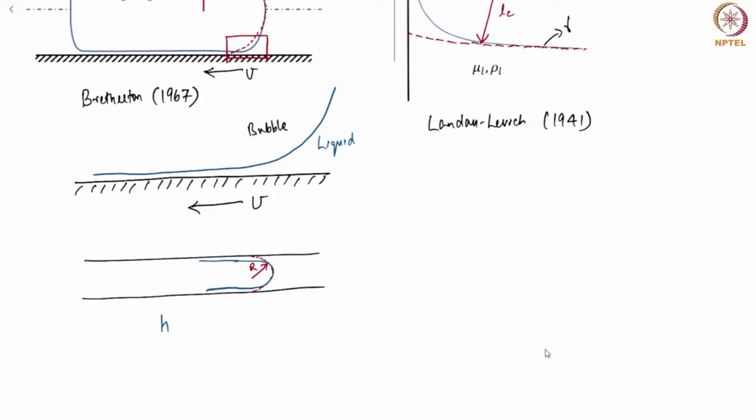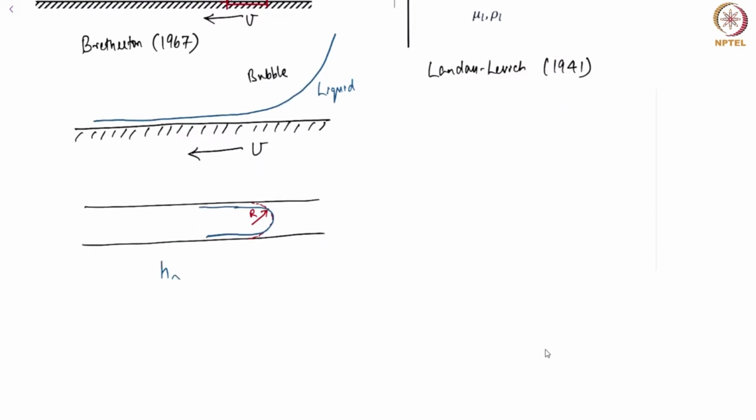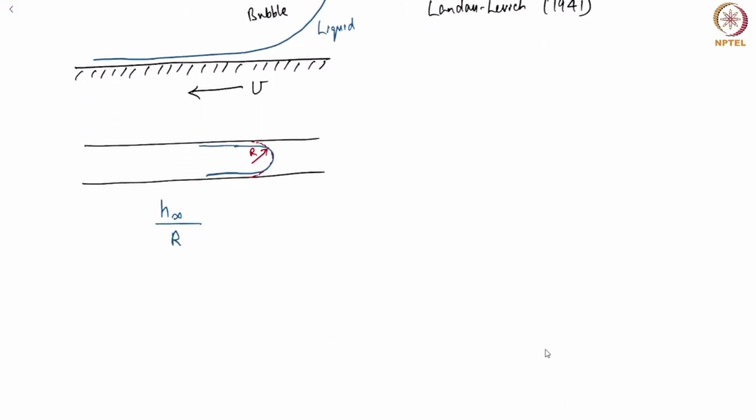So if one were to do exactly the same analysis as the Landau-Levich flow, then the thickness of the coating that you would get, now the outer region or the static region is given by the radius of the tube. This gives us 1.337 capillary^(2/3). Recall that the same analysis for the Landau-Levich flow gave us H by LC equal to 0.9458 capillary^(2/3).